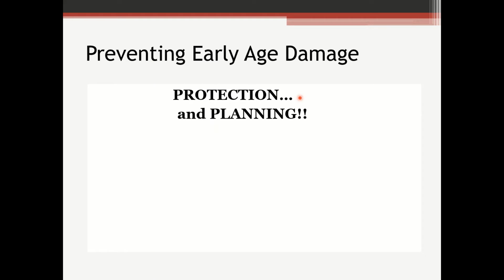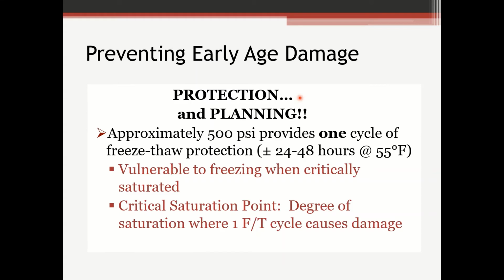So preventing early age damage, probably the most important thing is protection and planning. Planning for sure, you know, it doesn't just happen organically. About 500 PSI will provide us one freeze thaw cycle of protection. And we can usually get 500 PSI within 1 or 2 days after placement at about 55 degrees. That's a general guideline. Again, that's going to be specific to the mix. If you've got multiple freeze thaw cycles, that 500 PSI certainly isn't going to hold up to that. But one freeze thaw cycle at 500 PSI